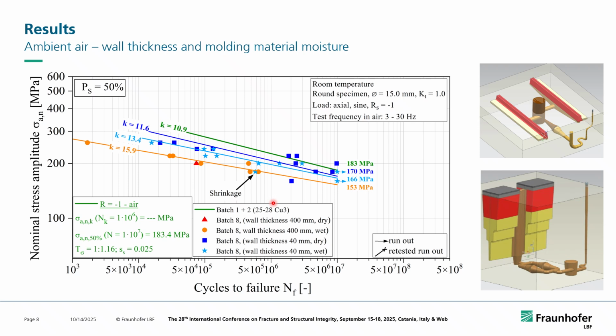At the end, what we saw here, both for the 400 millimeter and 40 millimeter, was not really an issue, whether we have a dry or a wet molding material. This was more or less the same fatigue strength here. But at the end, the 40 millimeter casting process here got the best results.